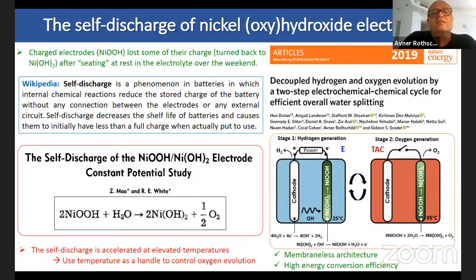What we also discovered is that this reaction can be enhanced at high temperature, which gives us a handle to control the oxygen evolution reaction. And with these notions, we came up with the idea of decoupled water splitting in a two-step cycle, where in one step, the hydrogen generation is carried out at ambient temperature, where you have the hydrogen evolution at the cathode like in a normal electrolyzer, but the anode is now this nickel hydroxide oxyhydroxide system that is simply being charged, and you stop the process when it gets to full charge.